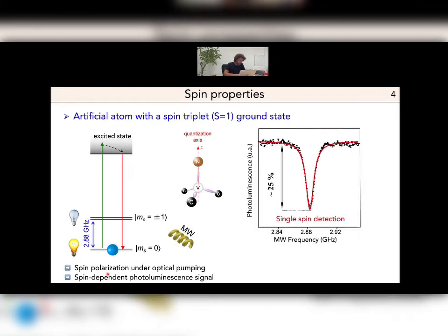These properties enable the detection of the electron spin resonance by optical means. To do that, we apply a microwave field, and when the frequency of the microwave is in resonance with the electron spin transition, it will transfer population from the bright state to the dark state, and as a result, you will have a drop of the photoluminescence signal. This is what you can see here, where the photoluminescence is plotted as a function of the microwave frequency. When the microwave is at resonance, you have a drop of the photoluminescence by something like 25%. And I insist here that this is the spectroscopy that is performed on a single spin.